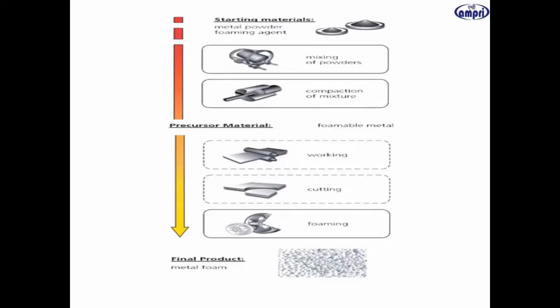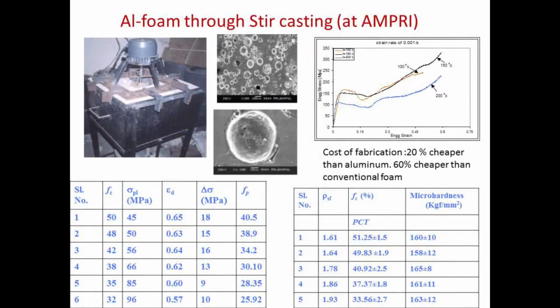This is a small kind of system we are using for the stir casting technique. We should have a stirrer at the top, and we should have a furnace, and a crucible within the furnace. Within the crucible we should melt, and after melting we should add the thickening agent. After adding the thickening agent we should add the foaming agent.